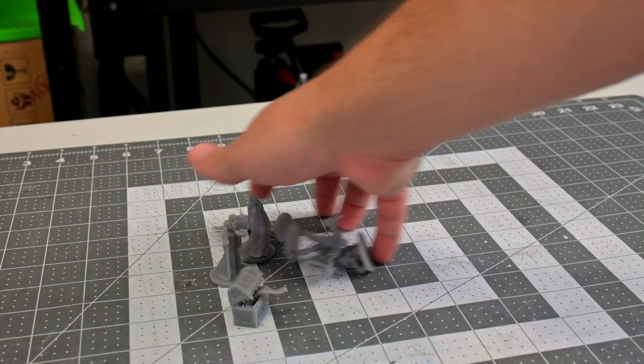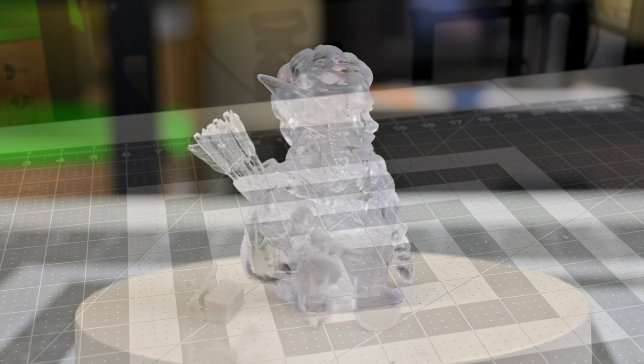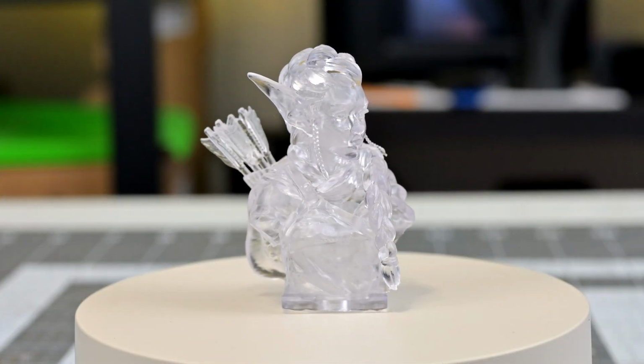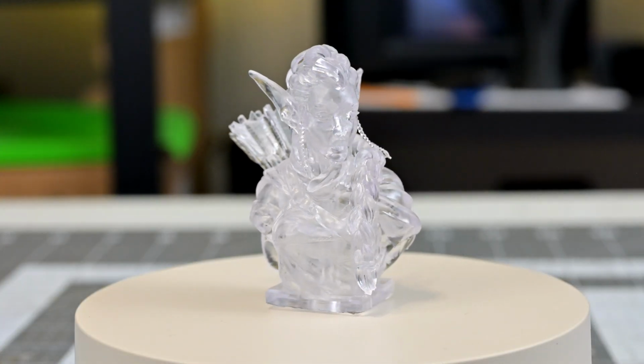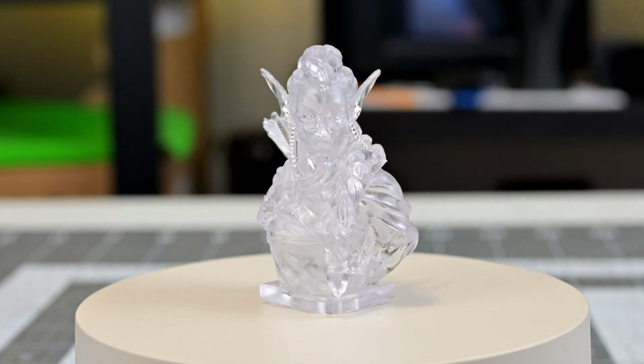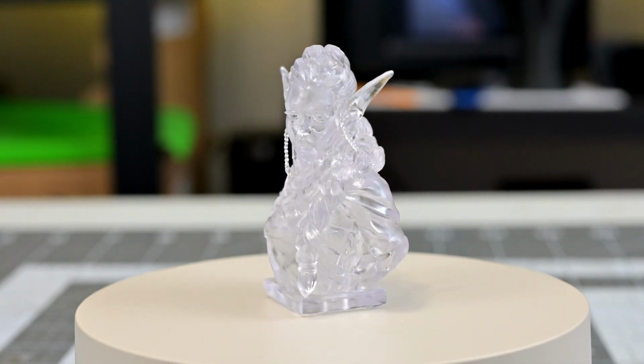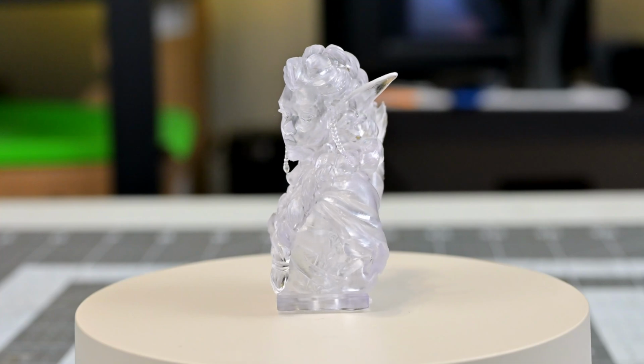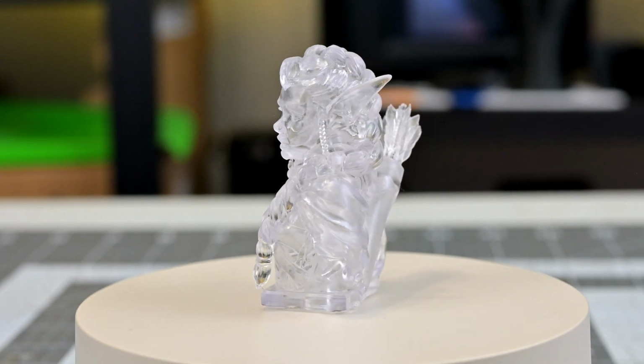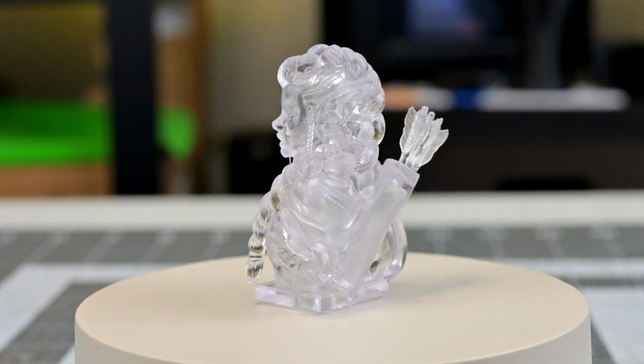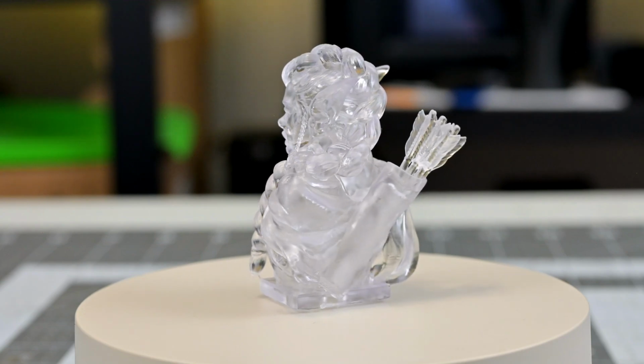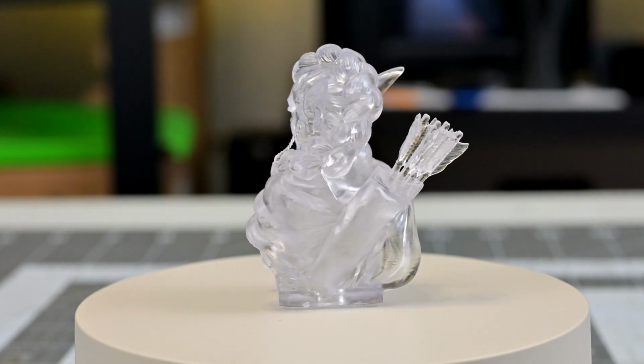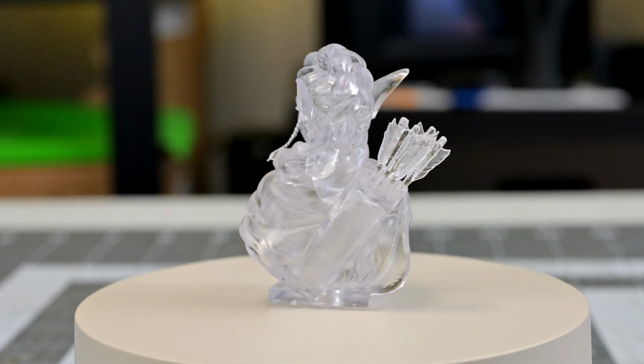The Creator Super Clear resin was just as easy to print and was actually low or no odor. However, it was much more difficult to remove from the print bed. A flexible print bed might help, as would finding the right bottom exposure times to get it to adhere just the right amount to your particular print bed. But the details of the prints are amazing, and the resin is truly clear after printing. And I haven't seen any yellowing in the few weeks since these parts were printed.